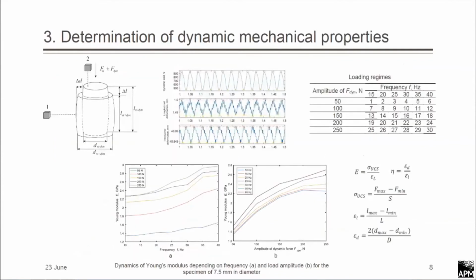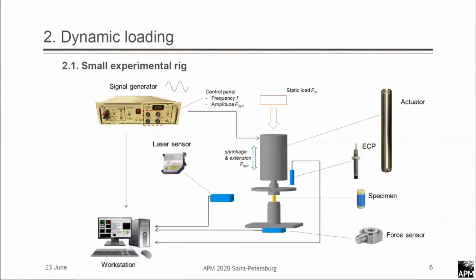On this slide, you can see how that sample was deforming during the experiment. Number one is a laser sensor, and number two is an eddy current probe. They were measuring longitudinal strain and transverse strain respectively. On top you can see the dynamic load as well. You may notice that the peaks of dynamic load correspond to peaks of longitudinal deformation. It also corresponds to the smallest peak in transverse deformation, which is quite logical if we go back to this setup: as soon as the sample shrinks, the space between the eddy current probe and this metal disc will increase. At the same time, the space between the laser sensor and the sample will decrease.